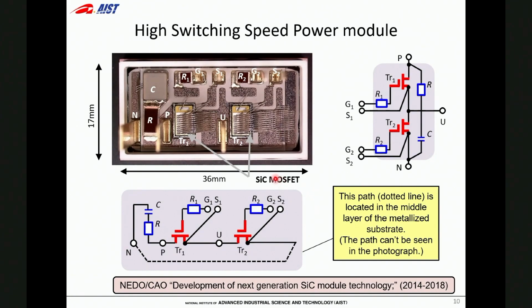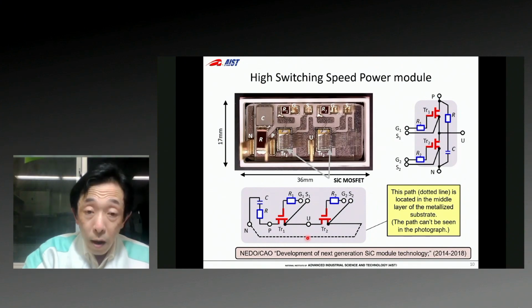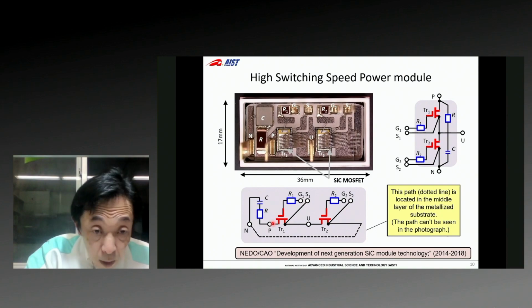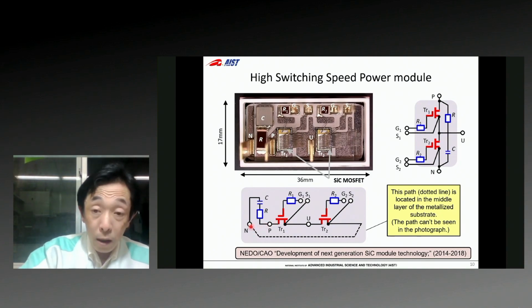To absorb the surge, a built-in RC snubber is introduced here, here, or here and here. The minimization of the parasitic inductance of the wire is also considered. In this case, the arrangement of the passives here is determined so as to minimize the wire inductances. For example, a dotted line shown here indicates that the path is located in the middle layer of the metallized substrate. As a result, the parasitic inductance between P and N terminals is about 4 nanohenry in this case.